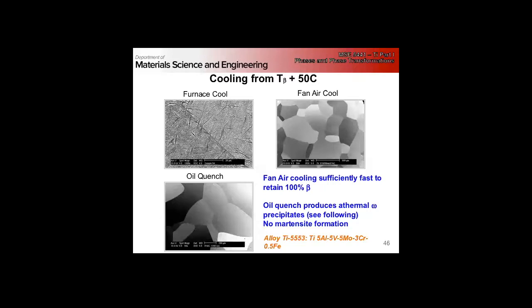So if we go, this is, I think, yeah, this is 5553, right? So 5 aluminum, 5 vanadium, 5 molybdenum, 3 chromium, and a little bit of iron, right? If we take it to the beta transus plus 50, and then furnace cool, so slow cooling, we get a basket weave type structure that looks very much like what we saw for the alpha beta alloys.